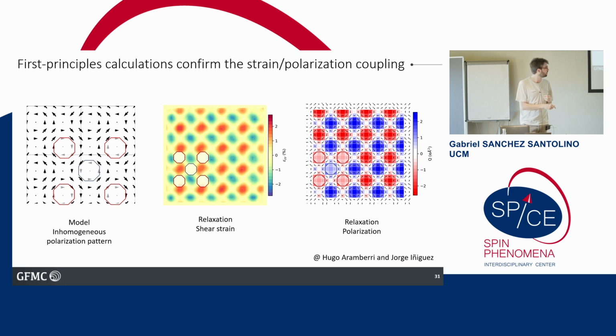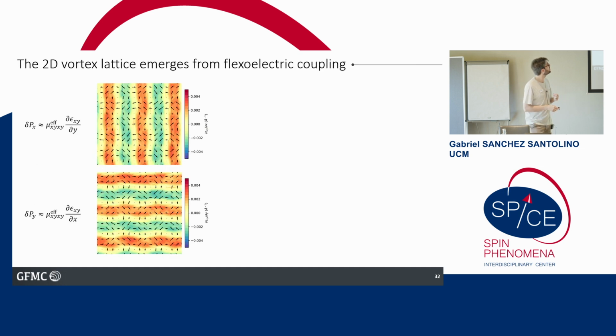And to explain all of these phenomena, we asked our theoretician friends Hugo and Jorge from the Luxembourg Institute of Science and Technology, and they did DFT calculations where they imposed the ferroelectric polarization and let the lattice relax, and we got the same kind of shapes, the same kind of modulations. The explanation for this modulation comes from the flexoelectric coupling. When you have a ferroelectric material, the ferroelectric polarization and the structure are always strongly coupled. So if you calculate the gradient of the strain along the vertical or the horizontal direction, this is going to be coupled with the ferroelectric polarization.